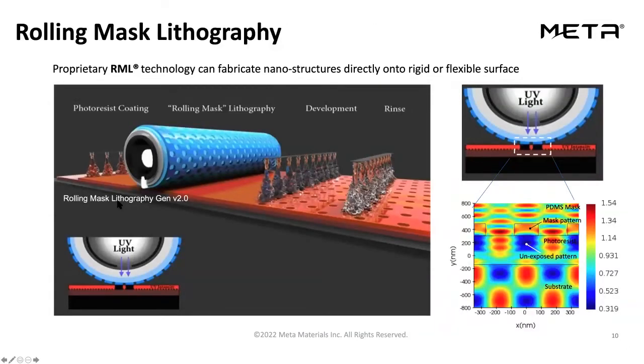As a different lithography technique to create metamaterial structures at scale, we have a proprietary technique called rolling mask lithography. I'm not going to go into the details of the system itself, but it is quite similar to a standard lithography process, which consists of photoresist coating, an exposure process, where we have the rolling element with a transparent mask, and then we develop and rinse, and then do metallization or dielectric coatings and a lift off process.